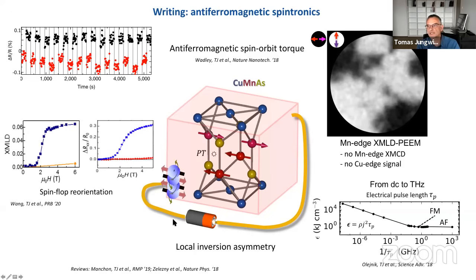Now, let me emphasize at this point that it is indeed very important when we study antiferromagnetic devices not to rely only on electrical detection, but to have a detailed image of what's going on with the antiferromagnetic order. Because the typical currents that we applied are relatively high, similar to ferromagnetic spintronics, there could be structural artifacts that contribute to the electrical signal. So having magnetic images is very important.